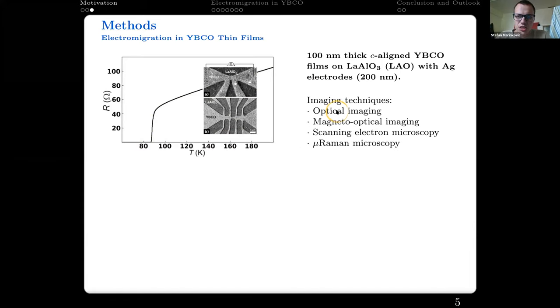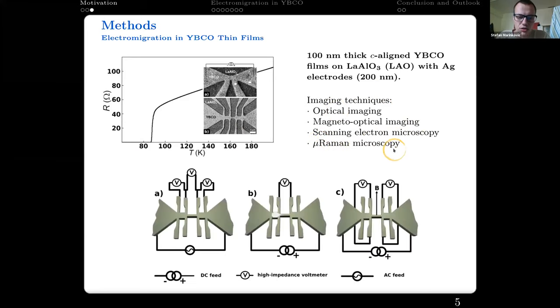We have used several imaging techniques, including optical, magneto-optical, and scanning electron microscopies, and also micro-Raman microscopy, and several electrical configurations to characterize our structures. Notably, we have performed electromigrations, temperature versus resistance measurements, and Hall effect measurements on the second, more complicated structure that I will talk about in a minute. First of all, we use this bow tie-like structure to inspect what happens with our thin film visually, optically, during electromigration.